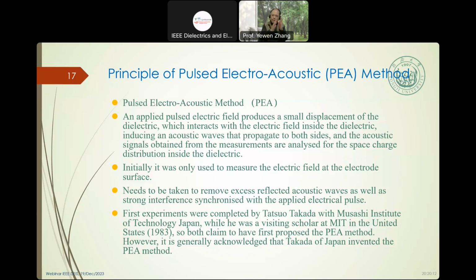So this one is pulsed electro-acoustic. We measure acoustic, but measuring acoustic is not very easy. It also needs electricity. It means the electrical change goes to the acoustic change and to the electrical again. So we can measure the electricity. Initially, it was only used for measuring at the electrode surface. It needs to remove the extended reflection of acoustic as well as the strong interference synchronous with the applied voltage, because if the applied voltage pulse is reduced, there is very strong noise, sometimes synchronous. So it's very important to separate this.